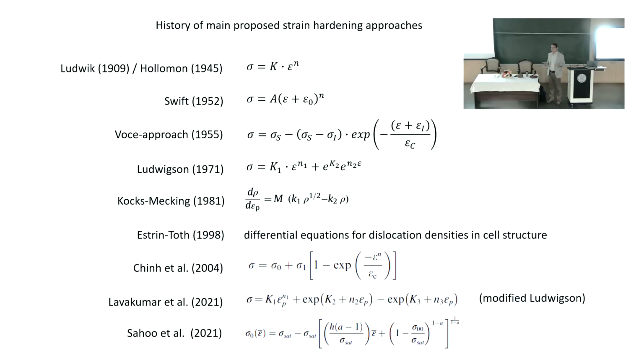In all my simulations for strain hardening with polycrystal plasticity, it was very successful. I was always amazed how such a modeling, which is not in the material but in the computer, produces exactly the same curve — not even different. So how is that possible? Then the idea was to make it at the macroscopic level as an analytical fitting function as well.